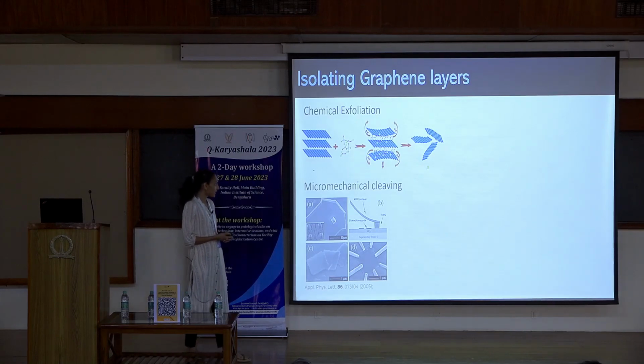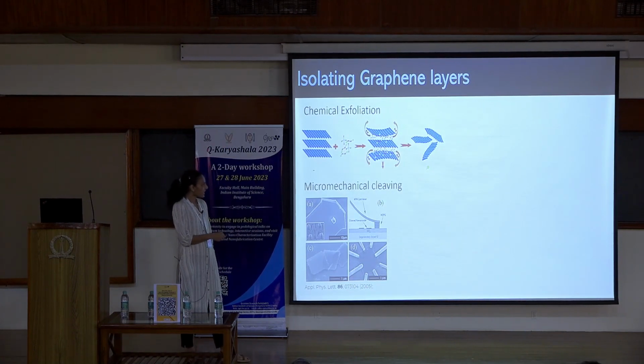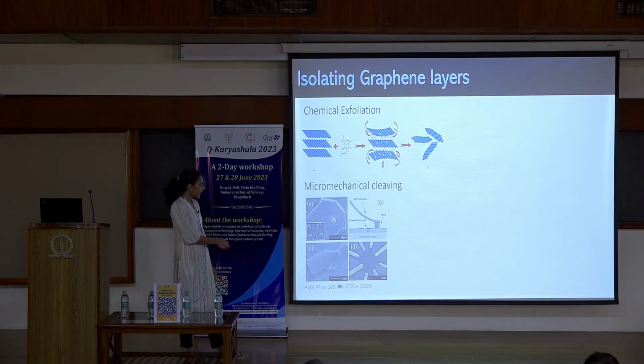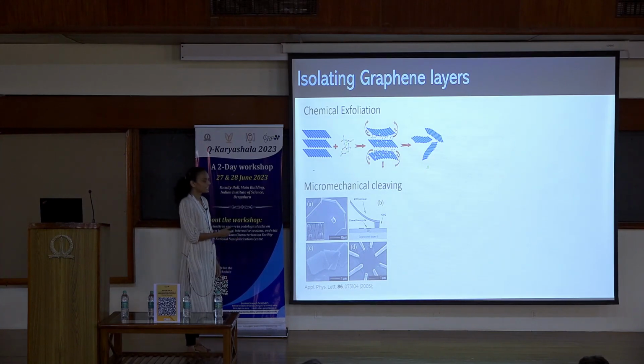Another very interesting technique, which was roughly the same time, it's very interesting, the history of how this material came about. You can see this is a 2005 paper. So around the same time there was another group which was trying to do this, and the way they operated was they took an AFM tip, which is like a small cantilever, and it had some amount of graphite in it. They brought this cantilever onto a wafer and they tried pressing on it. So their idea was that if I press it, maybe a few layers would cleave and be on the surface. And they were able to get these nice looking graphite layers, but they were not single layers of graphene. Okay, so they had a very nice work where they studied the properties as well, but they were slightly thicker, which is why this group didn't win the Nobel Prize, right?